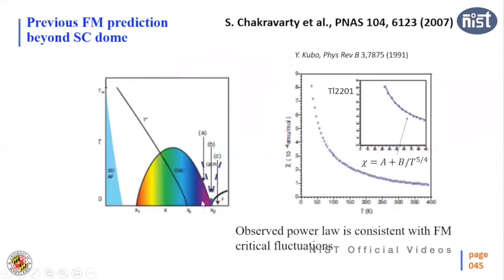He predicted that beyond the superconducting dome there could be ferromagnetism, and there is a quantum critical point. I won't discuss what a quantum critical point is. Based on the experimental evidence, the data that suggested this could be a possibility is this data. In thallium-2201, a hole-doped superconductor, the magnetic susceptibility as a function of temperature shows some strange behavior.